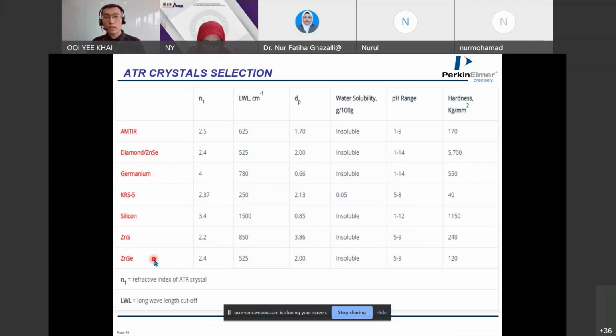So if you do not have any specific criteria to choose from, we always go with diamond, because diamond has the widest transmission range, meaning it covers the full IR range, 4,000 to 400, and the depth of penetration is around 2. It is inert, so you can run acids, bases, and ionic species. The most important thing is it's highly robust, meaning it's anti-scratch, so typically you wouldn't damage your crystals.